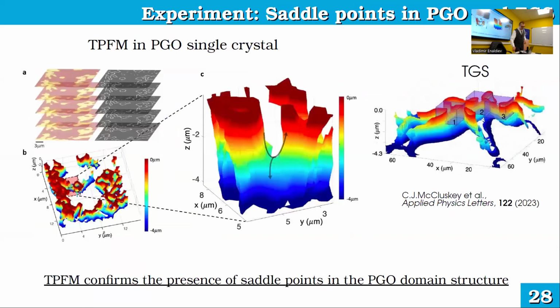And you asked about experiments. So maybe it's all model, it's all not true? Our colleagues made a so-called TPFM experiment inside the crystal. TPFM is tomographic piezo force microscopy. It consists of mechanical removal of layers of material with the tip of the microscope and simultaneous piezo force microscopy scanning. Upon removing the material, you get a series of scans, and using simple calculations, you can actually produce the three-dimensional structure of the domain wall in the volume of the material. And what they found out is that the structure of the domain wall in this crystal is really a singly connected surface, and it's full of these saddle points.